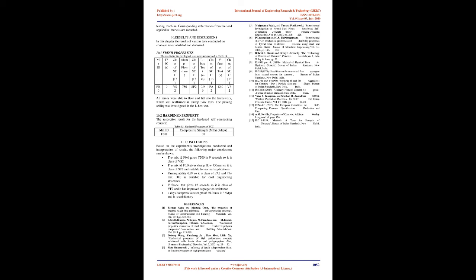9.3 Flexural Strength Test. The flexural strength test was carried out on a prism specimen of dimension 100 mm x 100 mm x 500 mm as per IS 516. Beams were cast to measure the flexural strength after 28 days. The flexural strength of specimen shall be calculated as Equation 4.3. Flexural strength equals PL/BD², where P equals load applied on the prism, kN. L equals length of the specimen from supports, mm. B equals measured width of the specimen, mm. D equals measured depth of the specimen, mm.